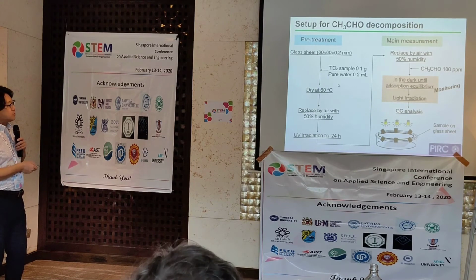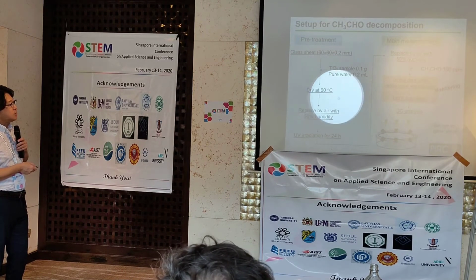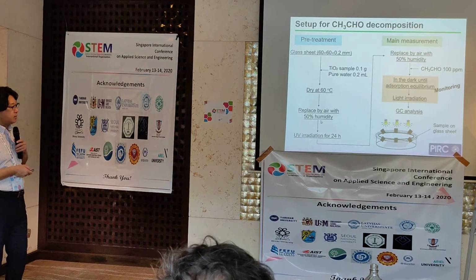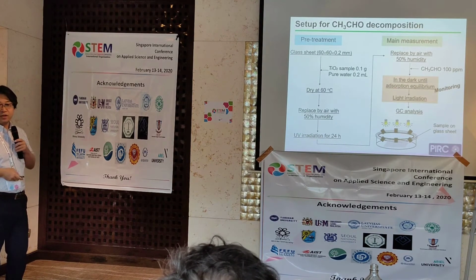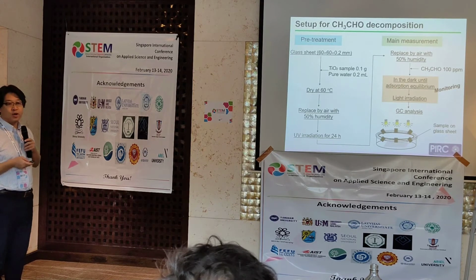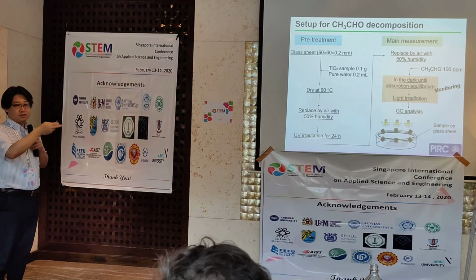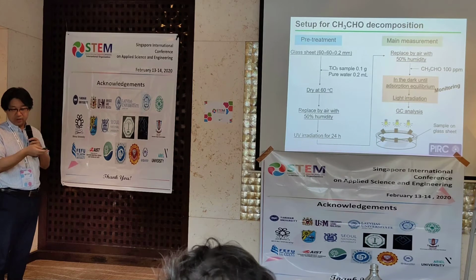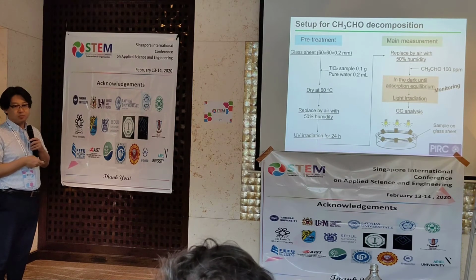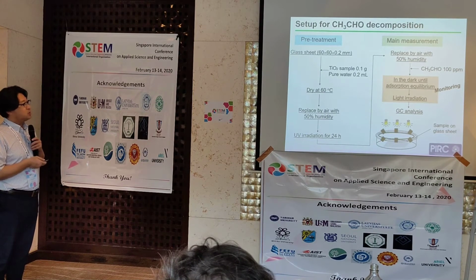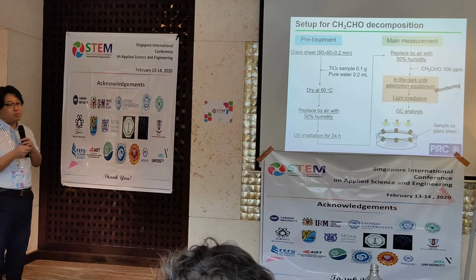So firstly, on the glass sheet, this photocatalysis material is dropped in pure water and dried at 60 degrees, then replaced by air with 50% humidity. Then UV light irradiates for almost 1 day to remove some chemical impurities. Then we go to the main experiment, again replaced by air with 50% humidity.